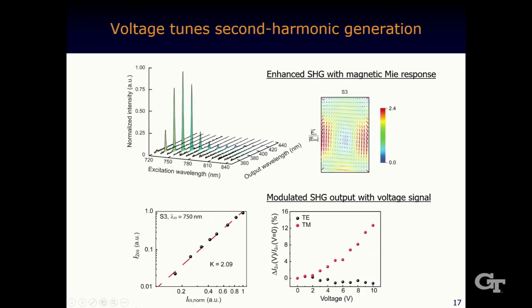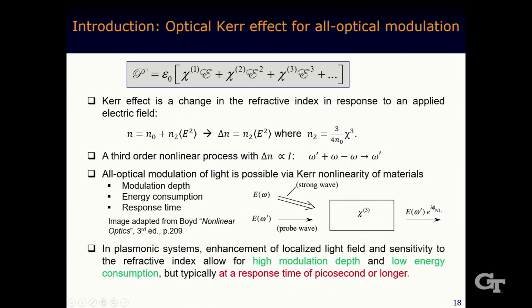And then in terms of modulation, without such a Mie resonance, for example for the polarization without the excitation of the Mie resonance, there's almost no tunability. And for the right wavelength together with the right excitation mode, you can see that the harmonic generation can be very sensitive to the applied voltage, as represented by this red dot.